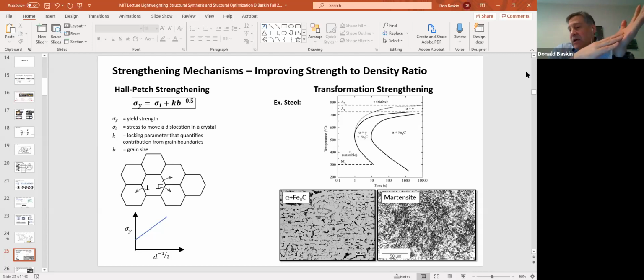His second company is called Veloxint. They're out in Framingham, and they use a similar strategy to make the material thermodynamically stable and make sure the grain size stays constant and the strength stays high. But instead of using electrodeposition, they use powder metallurgy techniques. They have powders that are already nanocrystalline, stable nanocrystalline on their own, and then they consolidate those powders through a sintering process. Because of the thermodynamics, the grains continue to stay small, and the material has an incredible increase in strength.